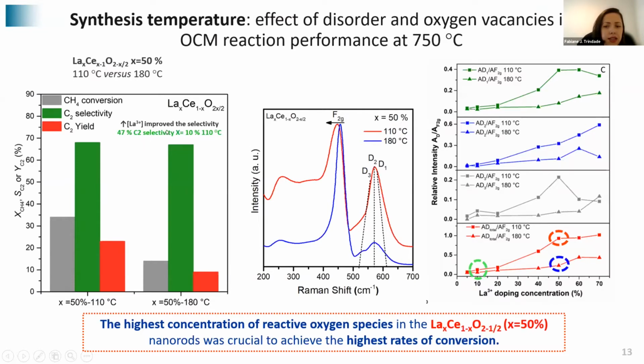Here, going back to the sample with 10% lanthanum synthesized at 110 degrees, where the amount of oxygen vacancies was not so different from the sample at 180 degrees, there was about 47% selectivity. And then the sample synthesized with 50% of lanthanum at 180 degrees achieved a similar selectivity to the sample synthesized at 110 degrees.